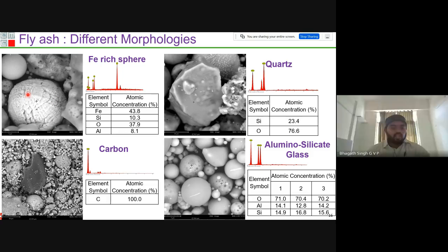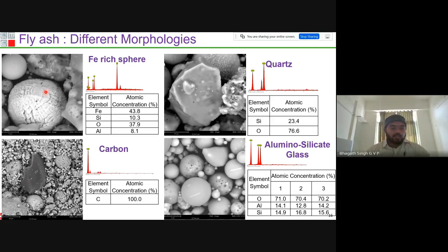There are also some individual particles I have observed in our fly ashes. I have observed a whitish grit on the particle surface, and these types of particles are classified as iron-rich spheres. I conducted EDX analysis on various particles to determine what product type is present in them. I also observed particles with very sharp edges, and these are classified as quartz. It is rich in silica. And the blackish particles are classified as carbon particles. It typically consists of carbon.